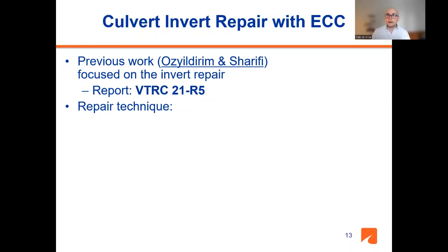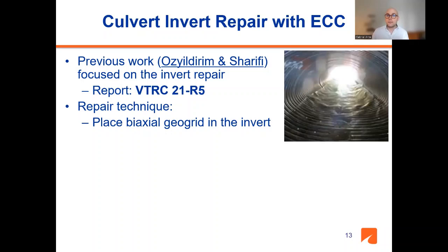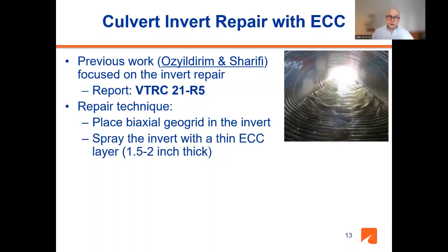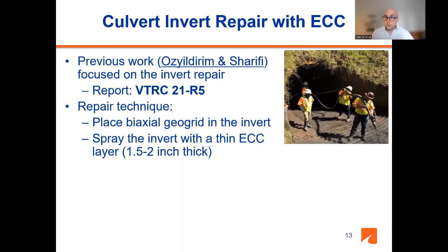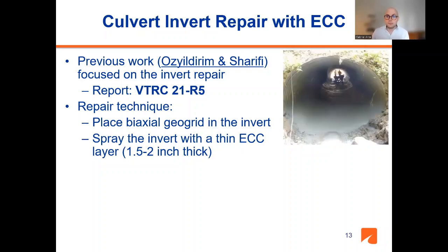In summary, what they developed is a repair technique for the culvert inverts, in which they started by placing a biaxial geogrid in the invert of this culvert. The purpose of this geogrid was first to allow the material to stay in place, since the ECC usually is quite flowable, and also to provide some reinforcement because this is a very thin repair. After that, they sprayed the invert with a thin ECC layer, about 1.5 to 2 inch thick. This is an image of the repair of one of these inverts, and you can see the culvert there, you can see the geogrid, and you can see how the workers are spraying the ECC into that invert. And this is the finished product.